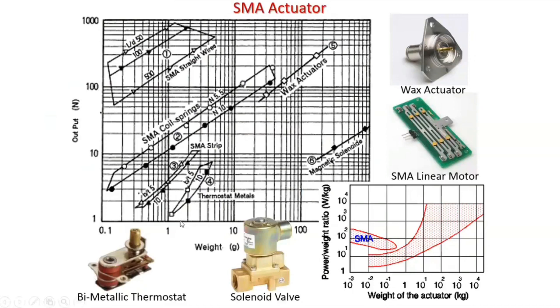On the other end of the spectrum, you have a bimetallic strip, the well-known bimetallic strip, where you have a difference of thermal expansion, and you get a very large change of shape, but you have a very low load. So the world in between is the world of possibilities if you look from the nickel titanium point of view, because nickel titanium has a high stroke of 6 to 8%, and it has a high load also, 500 to 1000 MPa, severely high as far as applications are concerned.